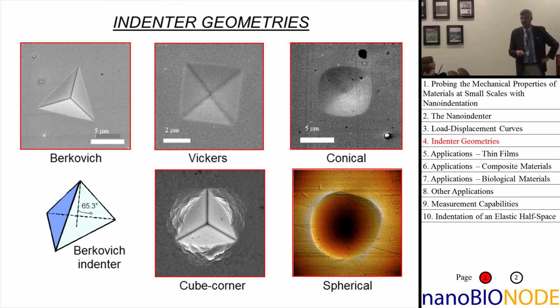Cones, in principle, are really, really important indenters to have. Because a lot of the modeling that we do is done with conical indenters because the axisymmetric nature of them makes them simpler. The problem with a cone is you can't get the diamond guys to grind you one that is geometrically very, very perfect. You can see that this one, there's some fourfold symmetry to that contact. That's because it's ground out of a 100 diamond, and the grinding itself is anisotropic.